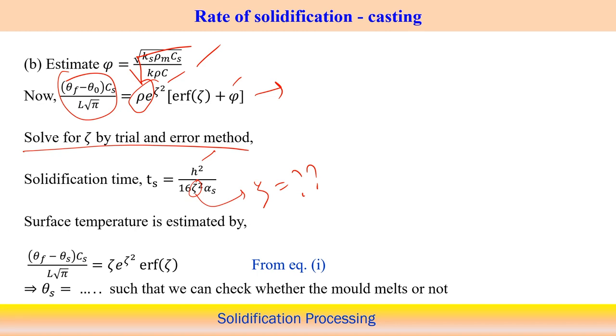Now, these are the two cases we can find out. Now, we can see in all these expressions, we just excluded the theta s, the surface temperature theta s, because we just eliminate the theta s and try to find out the relation in the known quantities. But theta s can be calculated in this particular case like that. We pick up any expression associated with theta s, and from there we can find theta f minus theta s by L root pi C s, that expression we have already given there, in terms of the error function zeta. So, from here we can find out the value of theta s, and when we calculate it, we can check whether the temperature theta s exceeds the mold metal temperature or not, then maybe the design of the casting process might not be appropriate if it crosses the melting point of the mold material. So, it is just a check to calculate what the value of theta s is, and from there we can check the status of the mold surface or mold metal surface.